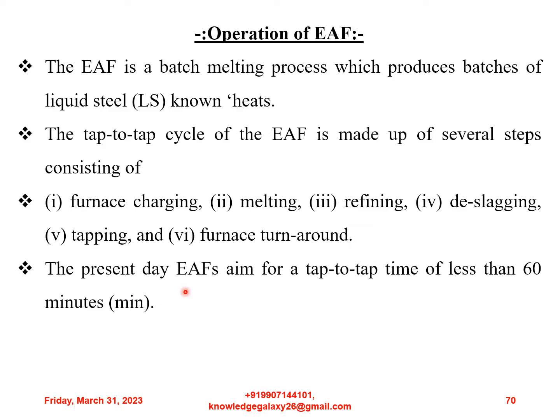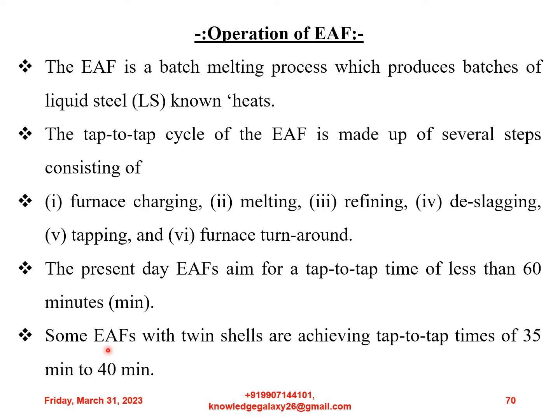The present day electric arc furnaces aim for a tap to tap time of less than 60 minutes. Some electric arc furnaces with twin shells are achieving tap to tap times of 35 to 40 minutes.